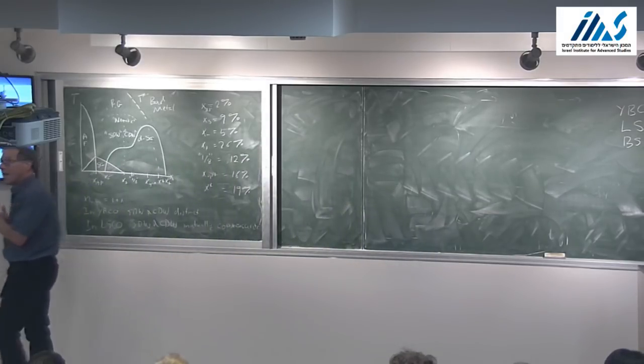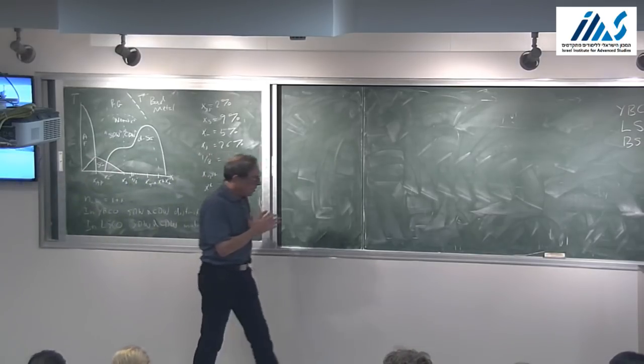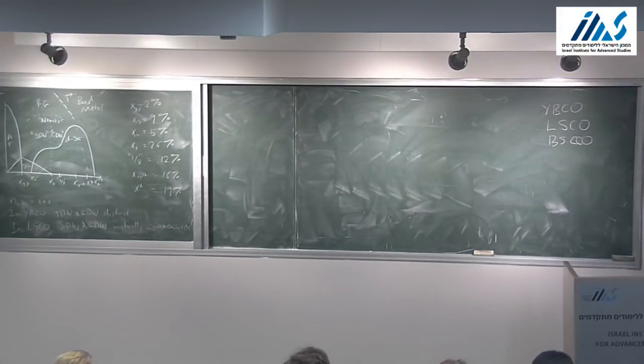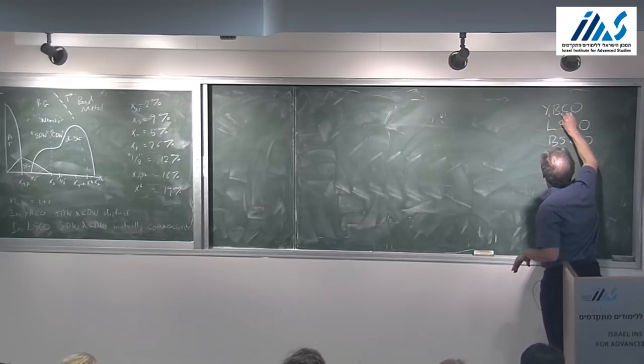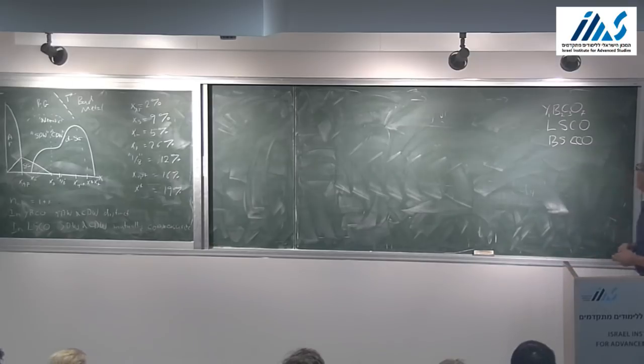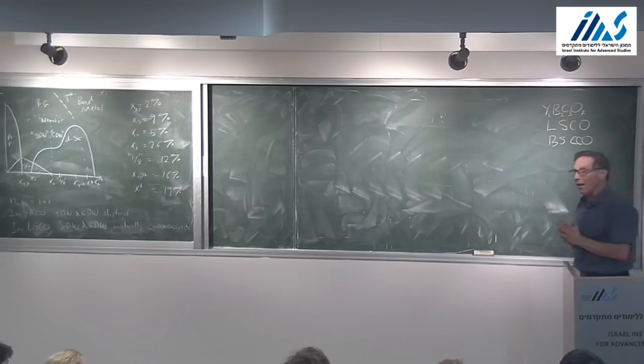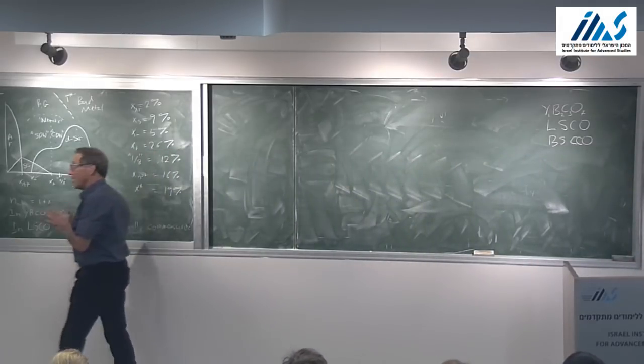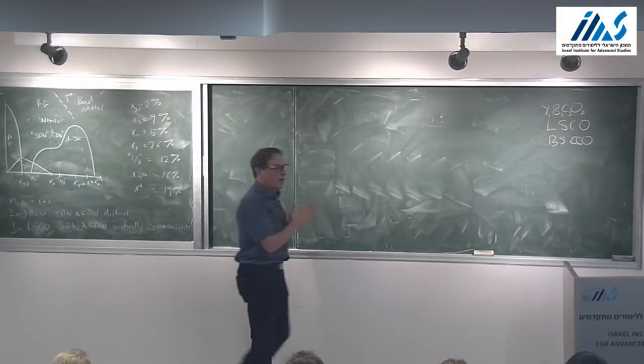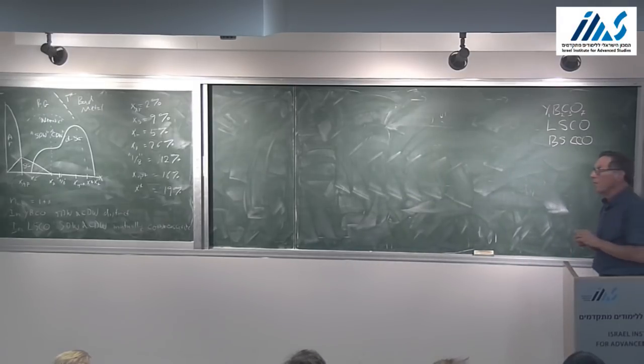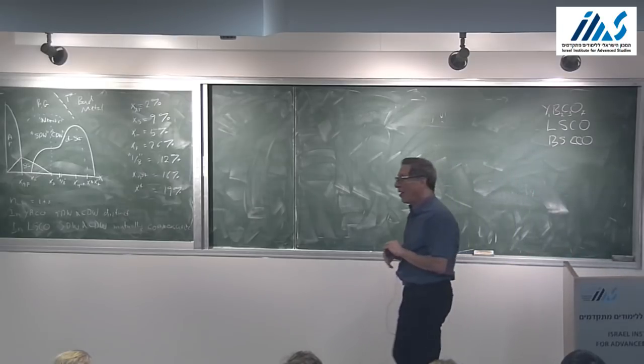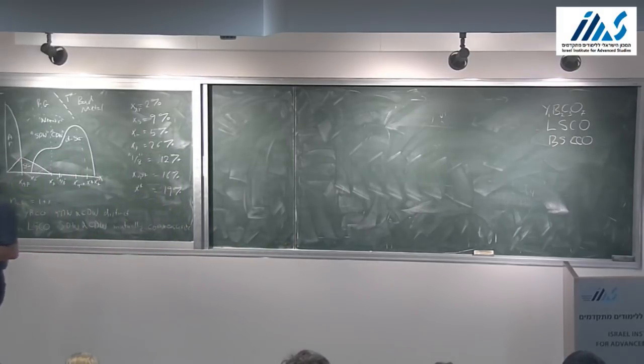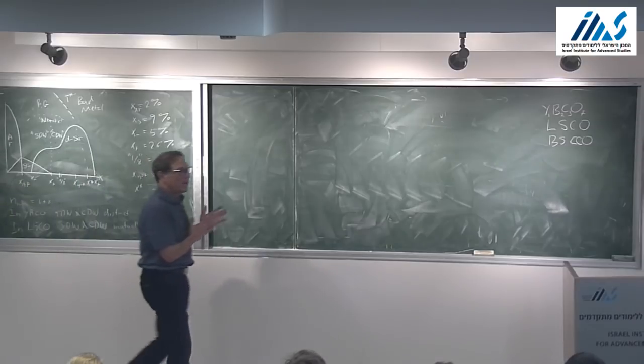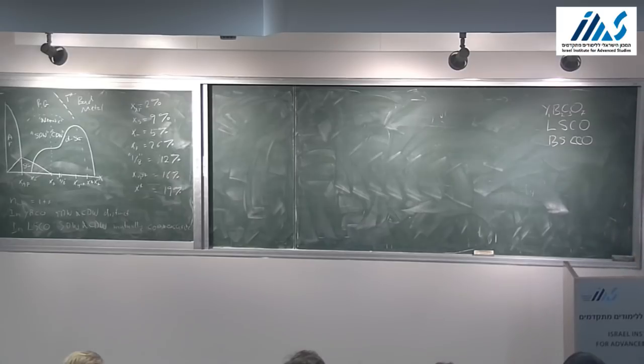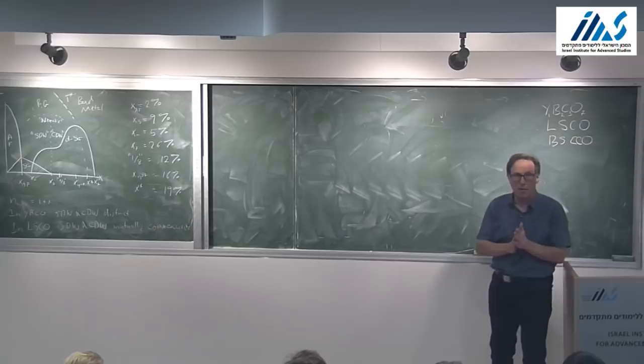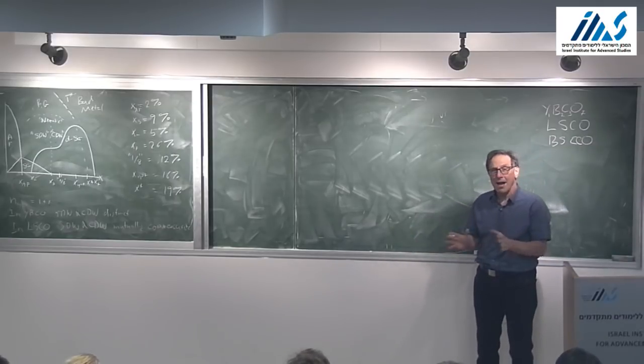There's one other thing that I want to say about phonons. These materials, as you can see, have complicated expressions. I haven't put the numbers in, but if we could, say, put numbers in here, we see that there are 13 atoms per unit cell, which means there are 13 times 3, I'm mathematically challenged, there are 39 phonon modes, and there are 2 electron bands at the Fermi surface. So there is some version of a large N theory that one might imagine is applicable to the electron-phonon problem in these complicated materials, in the sense that the number of phonon modes is enormous compared to the number of electron modes. Okay, and with that, I'm going to abandon phonons.